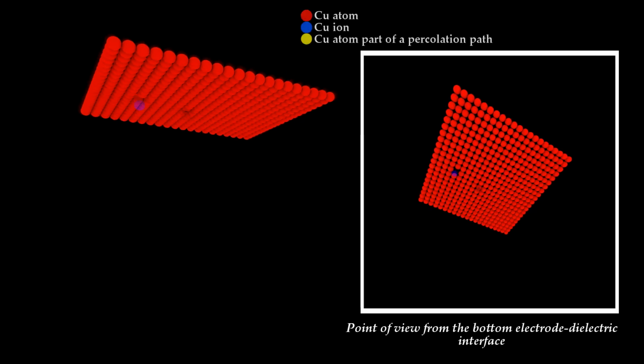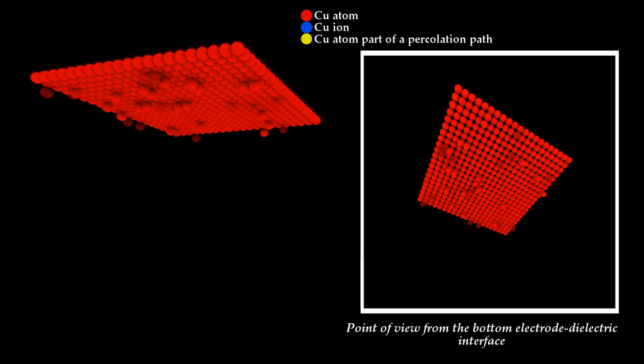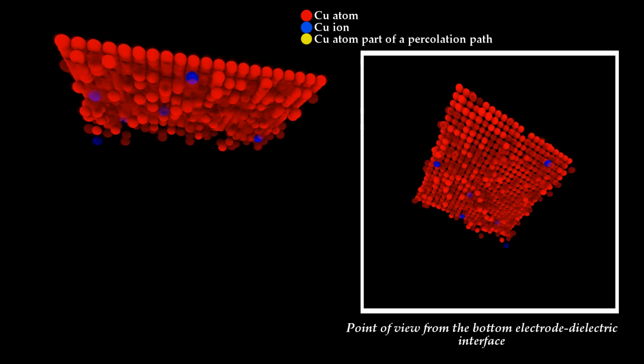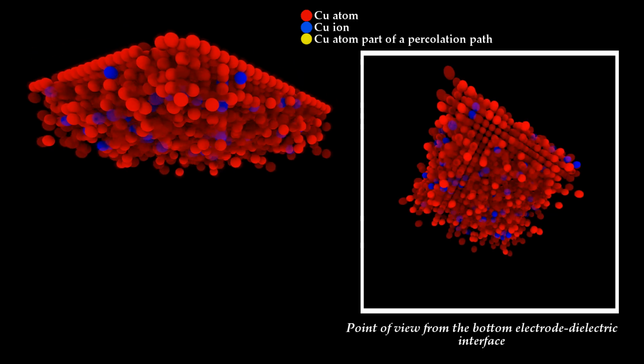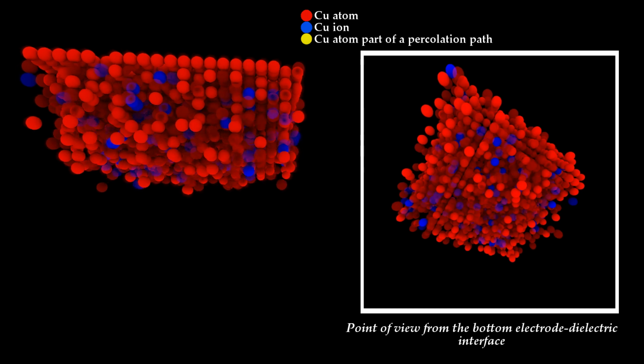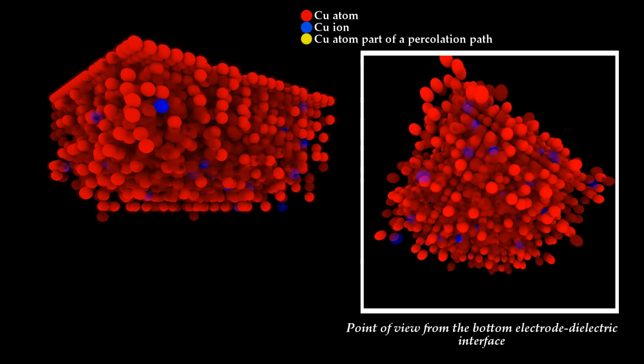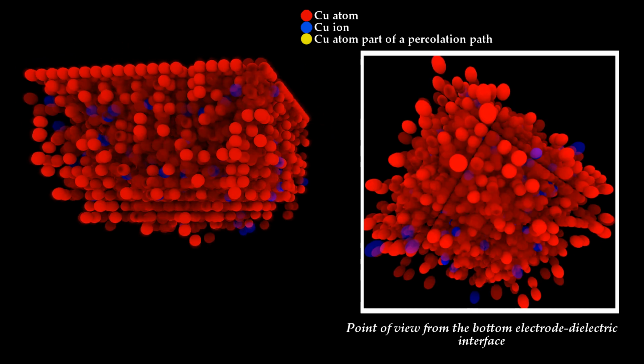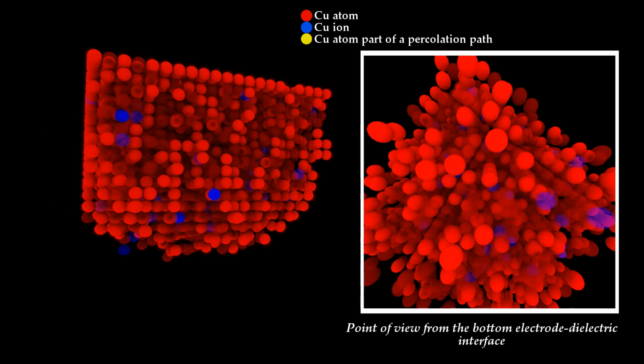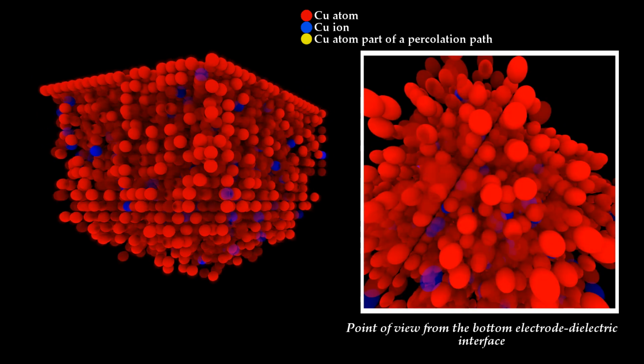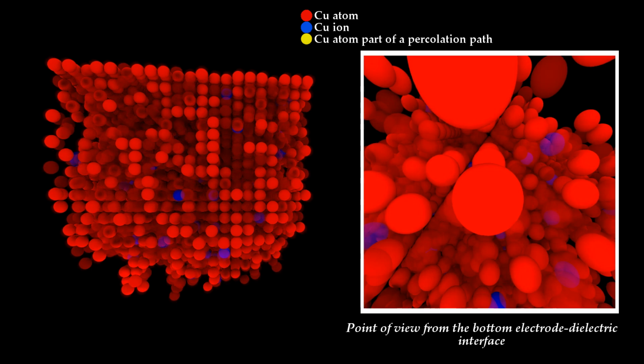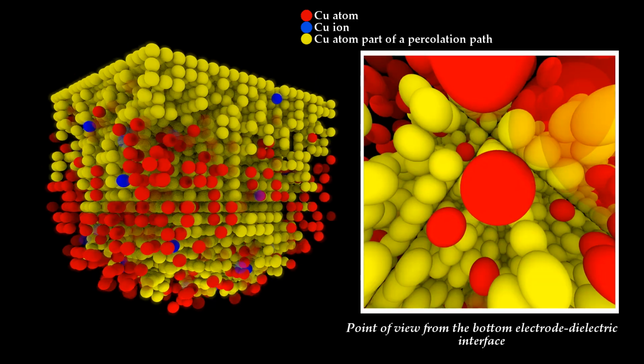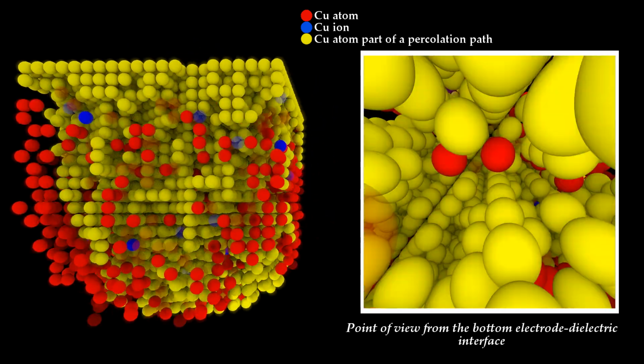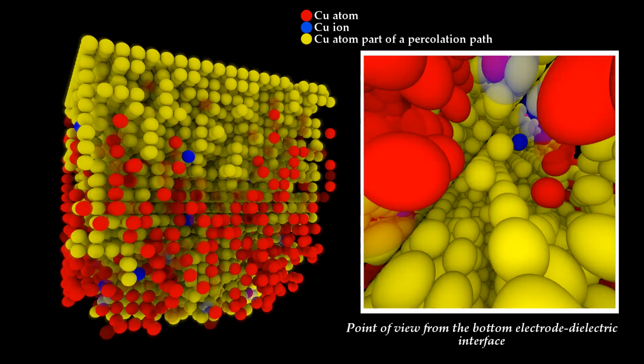The copper cations are formed at the active electrode dielectric interface. The cations can move because of diffusion and electric field-induced drift in the dielectric. The most important physical processes are included in the Monte Carlo algorithm. The reduced cations can form clusters, and if they keep on growing, the electrodes can be electrically shorted. If this is the case, a percolation path is formed.